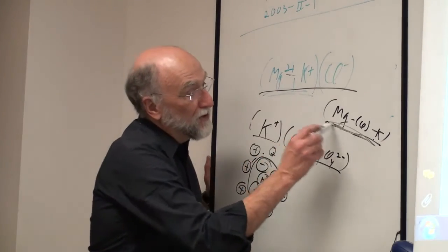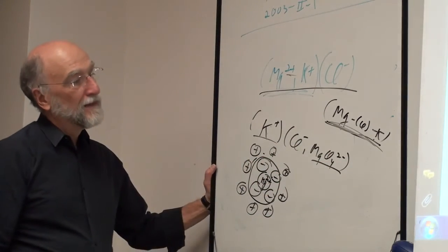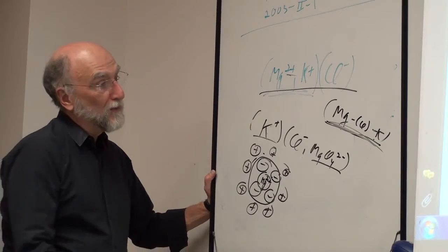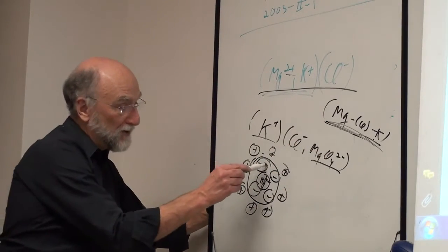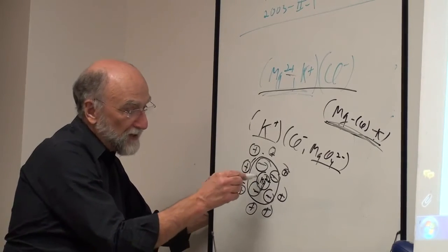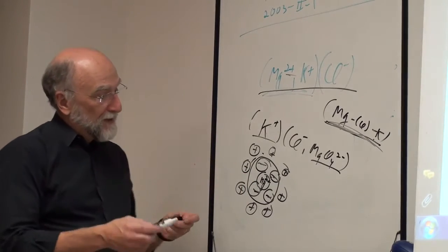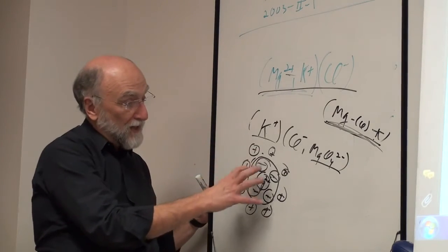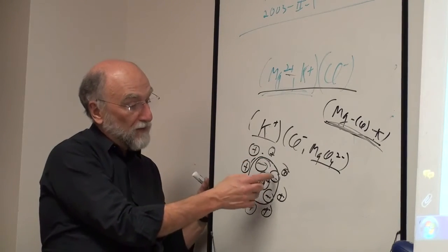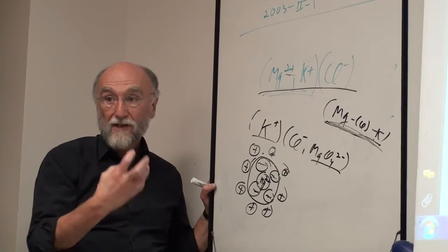And this is even observed. People say, well, you're using the quasi-chemical model, but people do Raman spectra or UV spectra of these things, and in these potassium chloride rich solutions they see vibrational spectra that are more or less what you would expect for an MgCl4 complex anion.